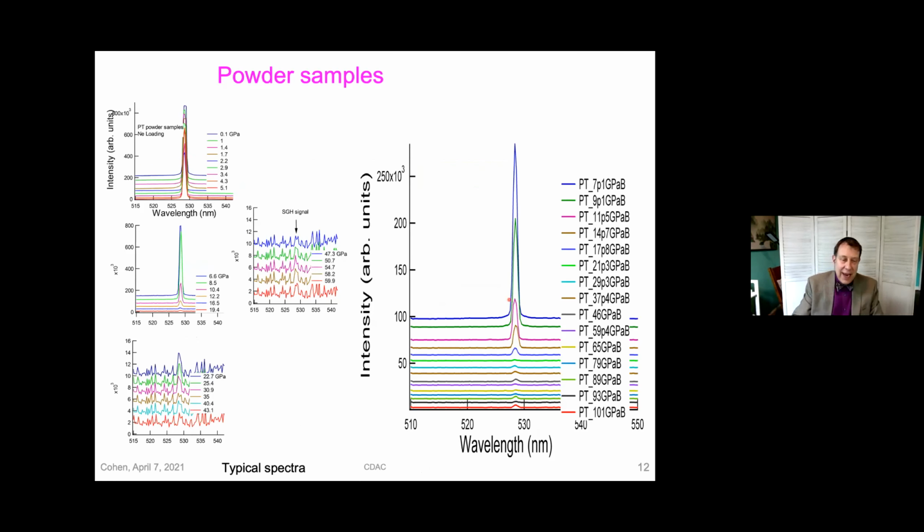So these are the actual data measured versus pressure. And this is from some years ago. And we've been trying to understand it ever since. So as he goes up in pressure, the signal goes down. And he looked real hard for signal at high pressure. So this is going up to 100 GPa. And maybe there's a little bump there. I'll talk more about this later. It certainly seems to get small in the middle. It certainly doesn't seem to be like what was predicted by Kornev and Balazs for this high pressure ferroelectricity. And so we were ready to say that there was no ultra high pressure ferroelectricity.